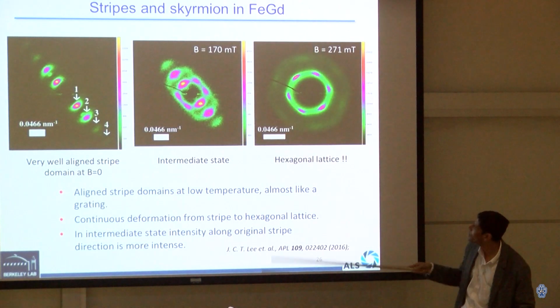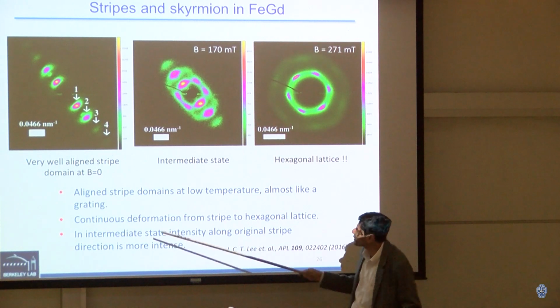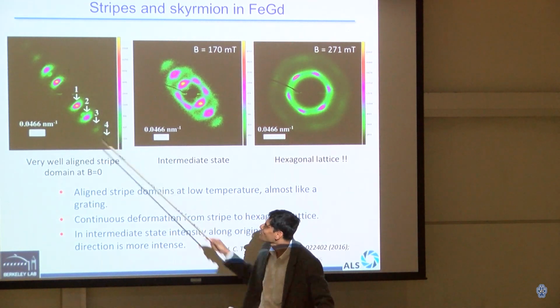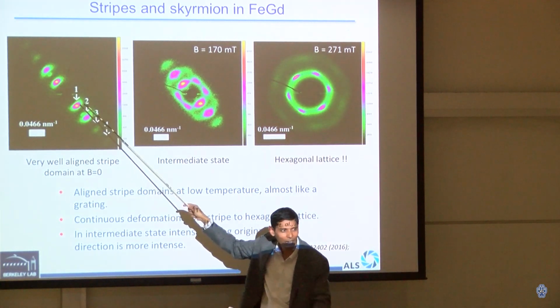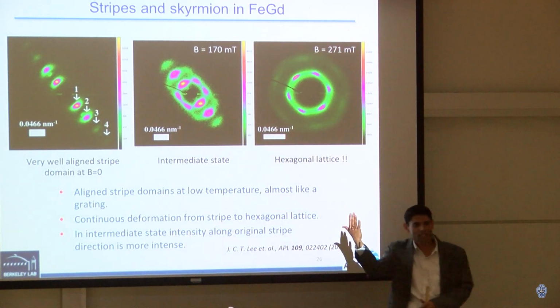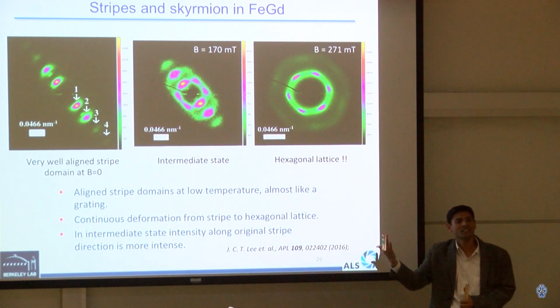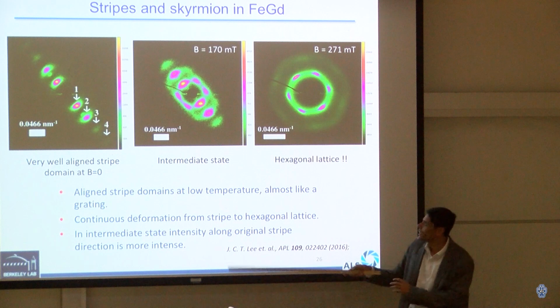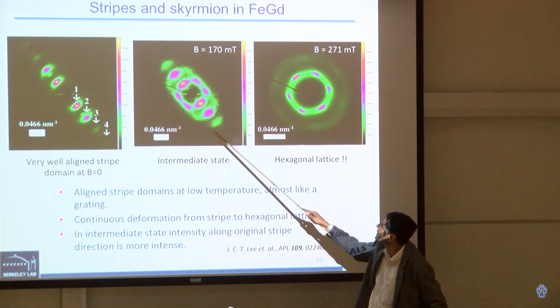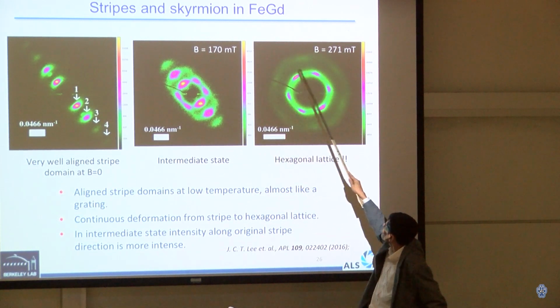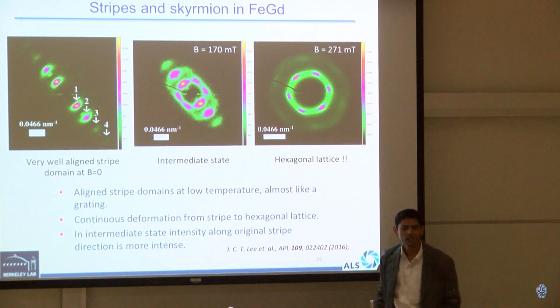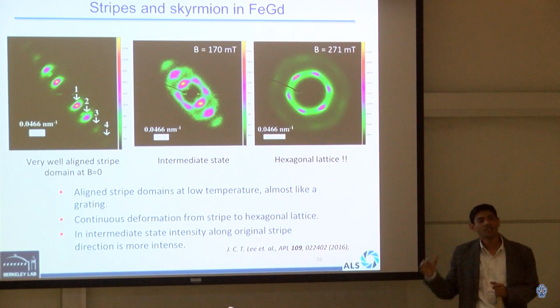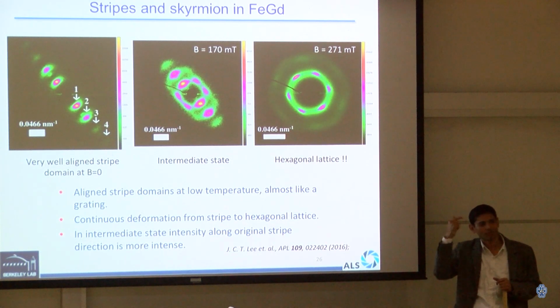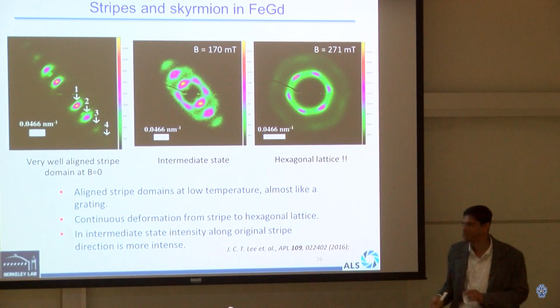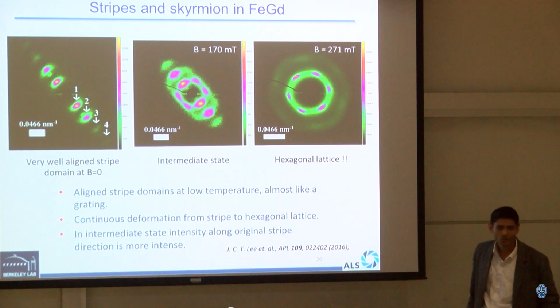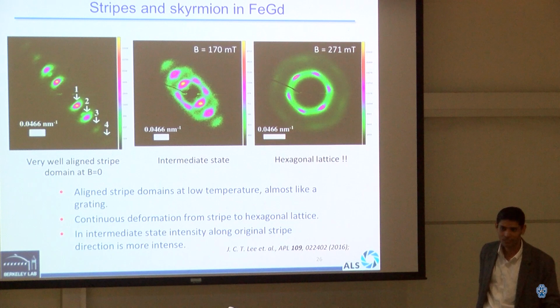That's what James did, putting in a lot of effort, I would think. And he got this fantastic magnetic diffraction pattern as if something is heavily aligned. So these are the domains aligned in the thin film sample. And then as he changes the field, he is getting nice structures and finally getting this beautiful hexagonal structure. And by now, hexagonal structure, aha moment for us, because is this a skyrmion? Because we know that a hexagonal structure can resemble a skyrmion.